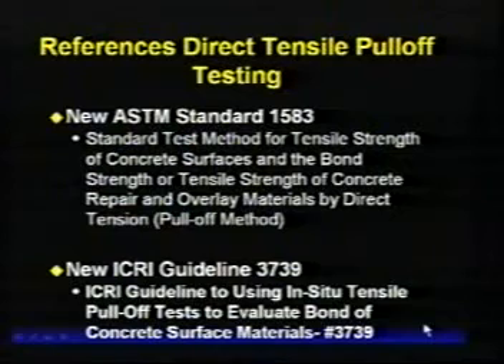There's actually two new guidelines for that referenced in this RAP document. The ICRI one is 3739 that just came out last year. It's probably the most complete, and it's designed specifically for the repair industry. It's not a modification of one of these tests used for something else. So the 3739 is probably the best one, and it goes through the procedures, it goes through the recommended values, and then ASTM has recently come out with one also that goes through an ASTM test method. So this is probably the most important quality control that we can put onto these jobs.